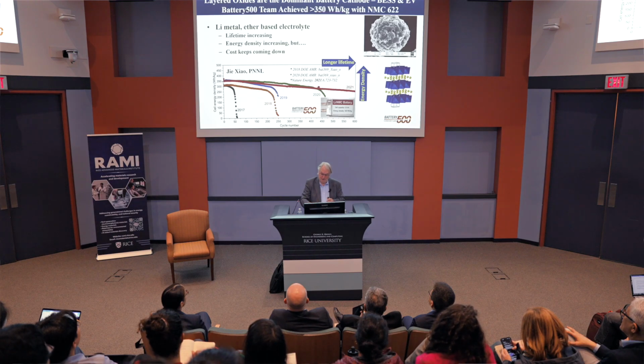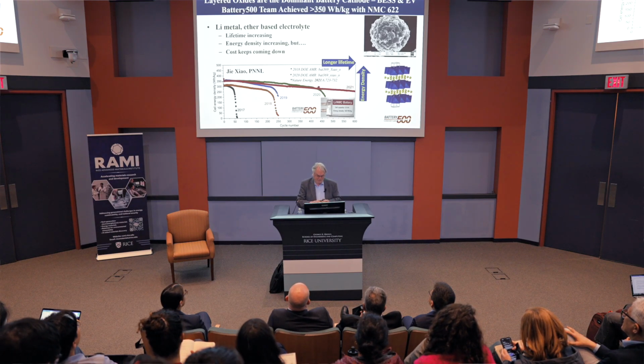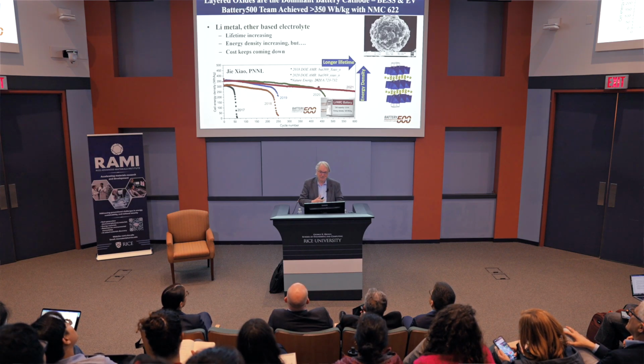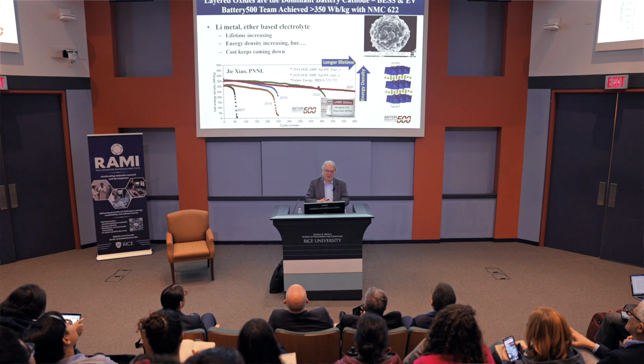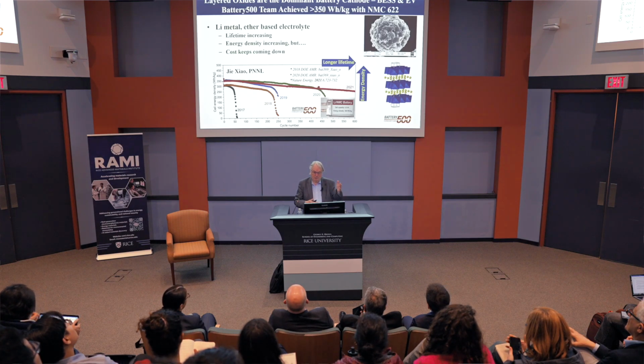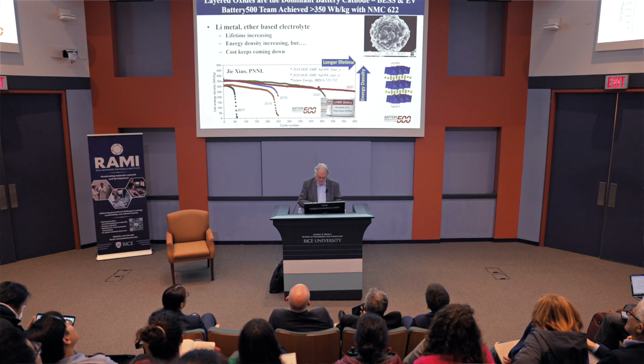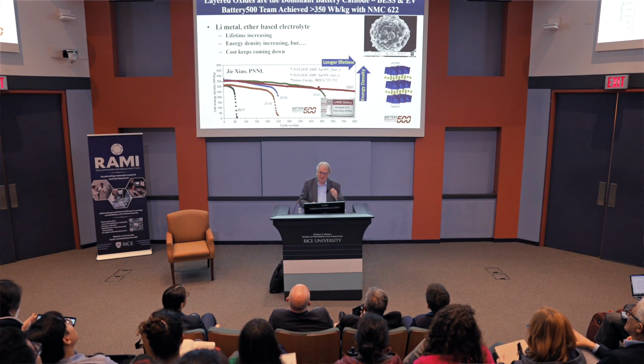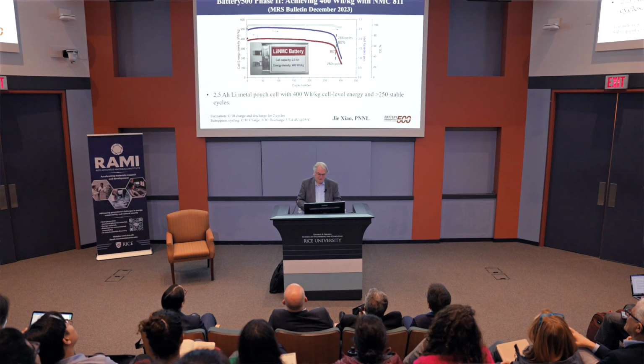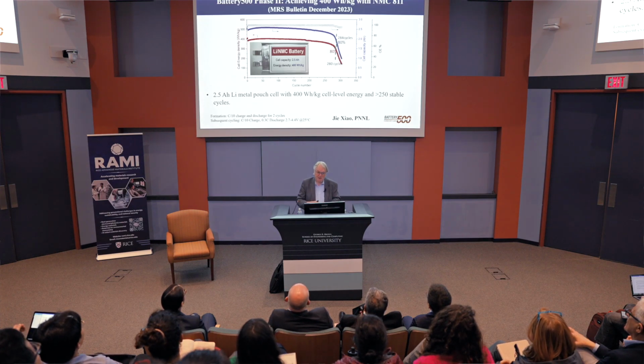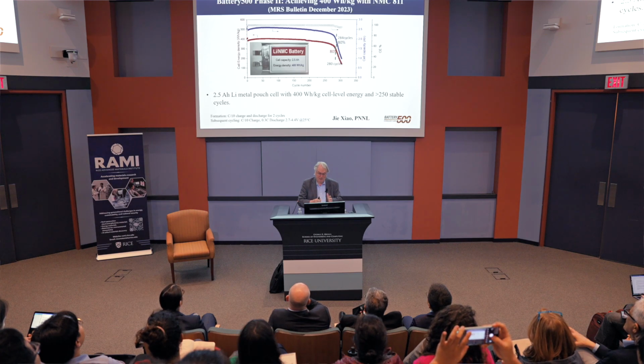So we're going for longer lifetime, higher energy density, and I should emphasize, you see this says NMC 622. This means 60% nickel, 20% manganese, 20% cobalt. And initially, way back when, these were equal amounts. So we're up to 60%. To get higher energy density, we need more nickel. And this is the present status, now 80% nickel in these. And this is published in December 2023. And you can see we've got 400 watt hours per kilogram for over 250 cycles.